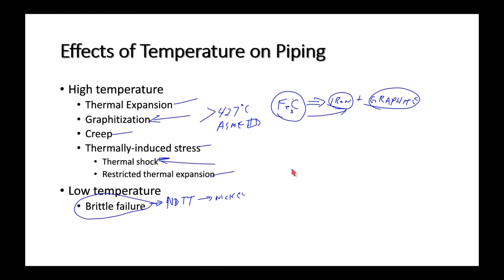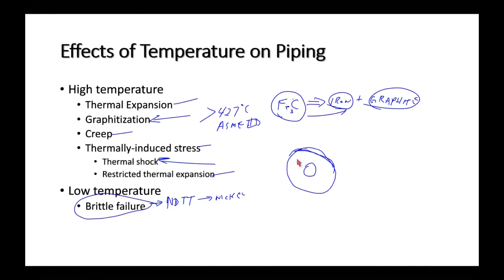And what about this one here, thermal shock? Do you guys know what that was? Let me give you an example of thermal shock, okay? This is a cold, high-pressure steam line. And it's really, really thick. It's exaggerated. Actually, let's say it's a steam chest from a turbine. Oh, no, this is piping. Okay, so it's got to be pipe. And when it's really, really cold, I can take superheated steam at 600 degrees Celsius and just blast it through there without warming up the line. What's going to happen is I'm going to get great thermal expansion, but it's going to be restricted thermal expansion right on the inside surface of that pipe. It's going to exceed the elastic limit of the material, and then the next time, when I turn off the steam and let the pipe cool down, I'm going to see cracks.